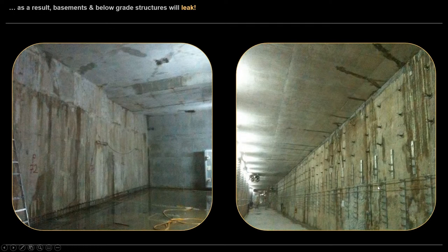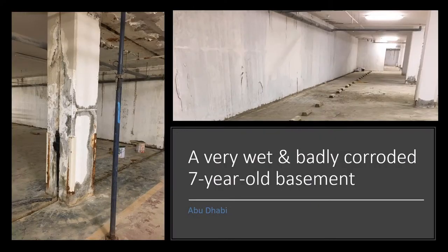The one on the right, that wall was reasonably well waterproofed with a membrane. The roof of the tunnel section was without a membrane, and basically water is just transpiring through the cracks, lateral cracks running across there and running down the face of the wall. They're both caused by membrane failure, essentially, and membrane failure is notoriously difficult to resolve.